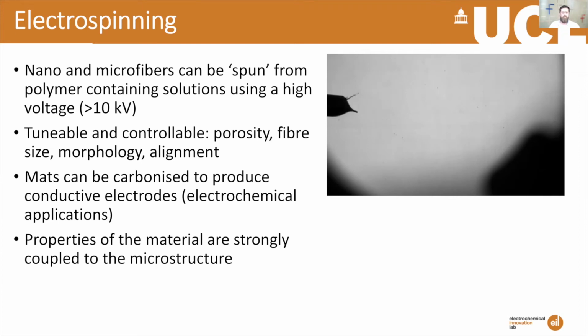The basics of the technique is you have a polymer that is slowly extruded out of a needle. The needle is charged, and you have some sort of collecting plate that's also charged, and there's a large bias voltage, normally over 10,000 volts, in between them. And this draws out the polymer into a sort of cone, and eventually it sort of shoots the polymer onto the target. You get this spinning process. You can see in this animation that it's kind of quite random.